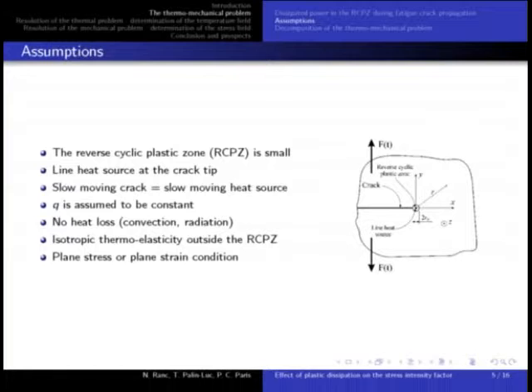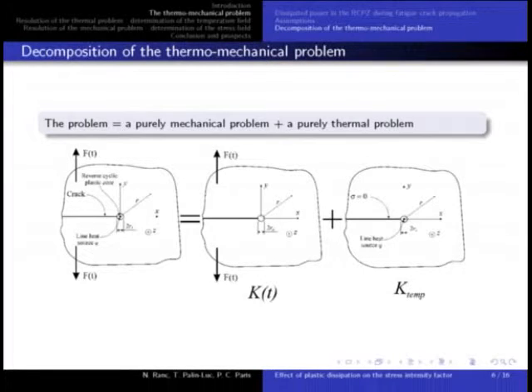So the problem we have to solve with the cyclic loading for the crack propagation is the following. There is a mechanical problem, the usual problem that all of you know, plus the thermal problem with the heat source at the crack tip, which creates a heat stress field and which will affect the stress intensity factor. I will call in the presentation K-temp, the temperature effect on the stress intensity factor.